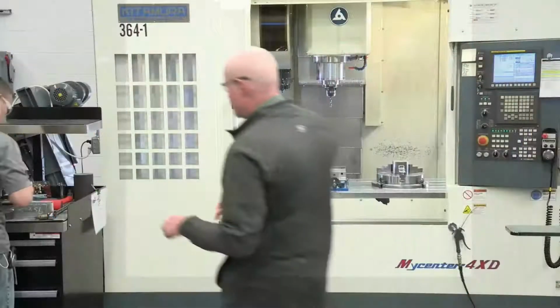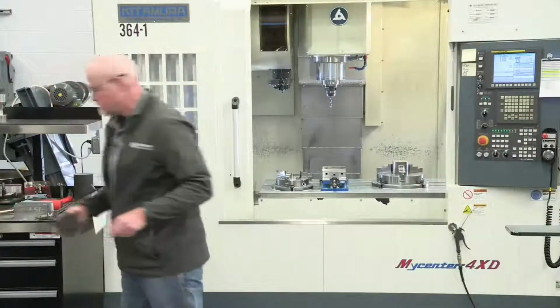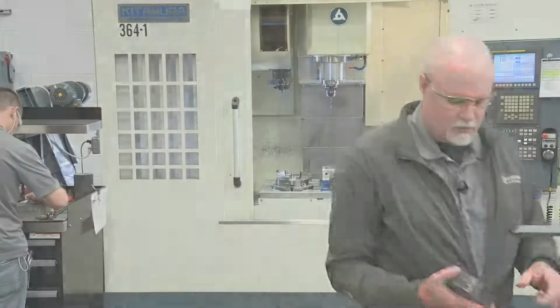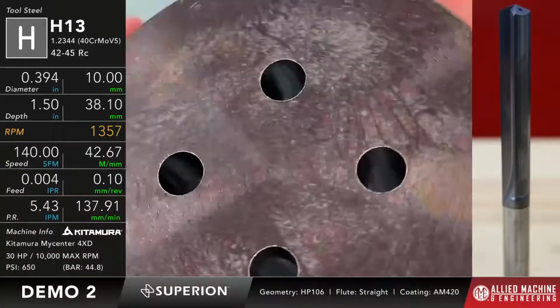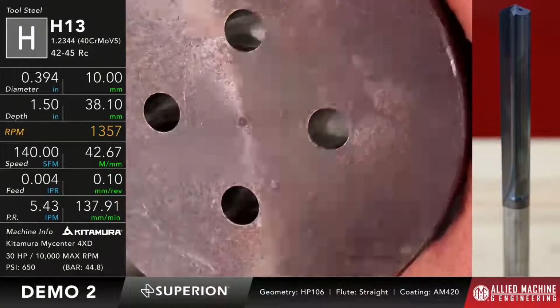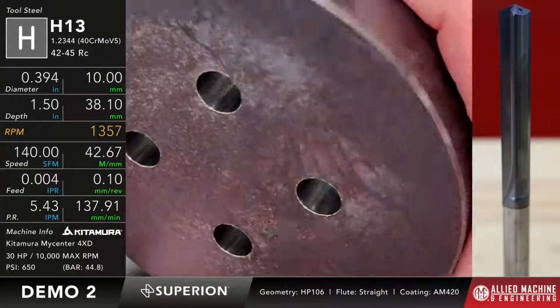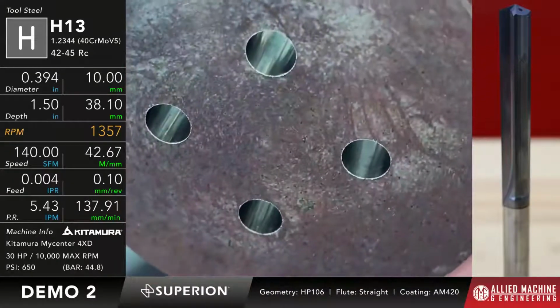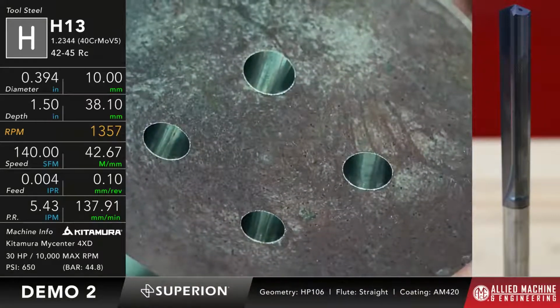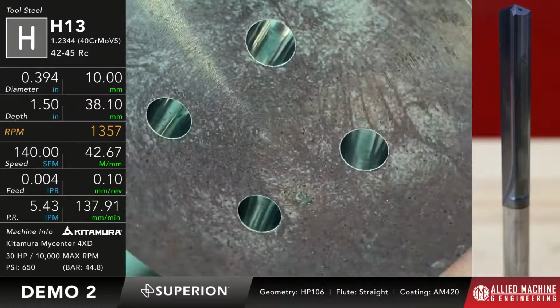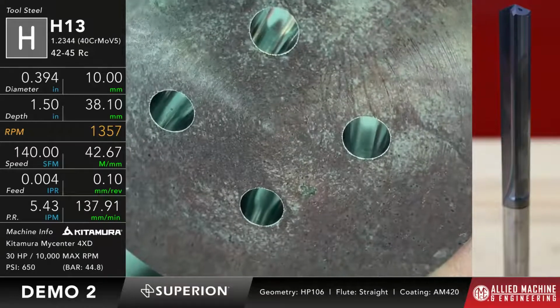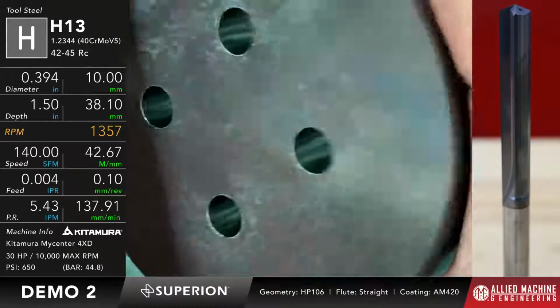Let me come over here and grab a piece of H13 while Dave's marking up which one of those aluminum parts we did. So this was the second cut that we made. This is that H13. It's about 45 Rockwell. So you can see the finish on this is really, really good. Once again, based on the hardness of the material and the fact that we're getting a really clean cut out of it, you can see that makes a really good quality hole.